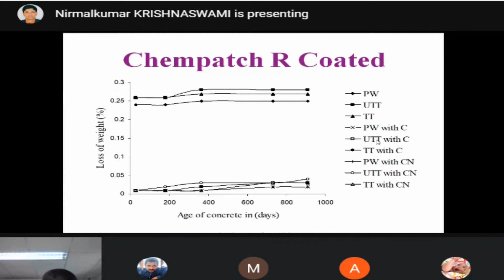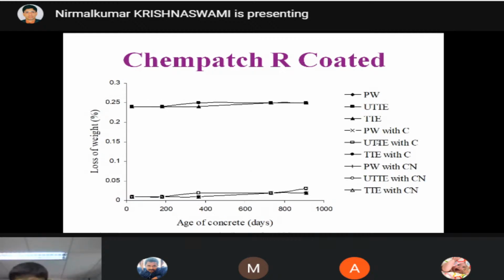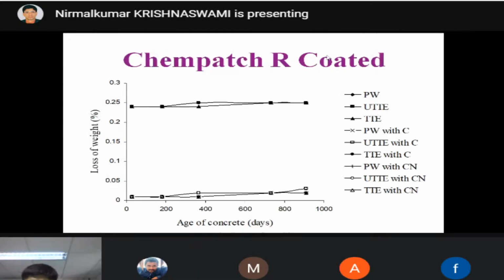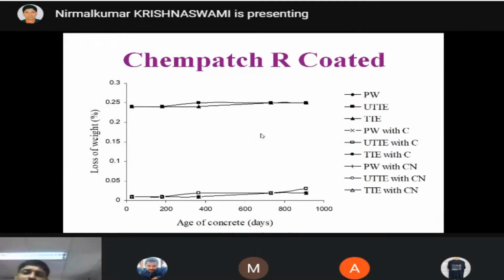This is for tannery effluent, and this graph shows the result for the textile effluent. If we coat this Chempatch R, corrosion is totally reduced. Even if you are not adding the admixtures, just if you coat this Chempatch R, the weight loss will be less than 0.3 percentage. But the only problem is after 3 years or after 5 years, you will be having corrosion. That is the reason we are adding the admixtures.